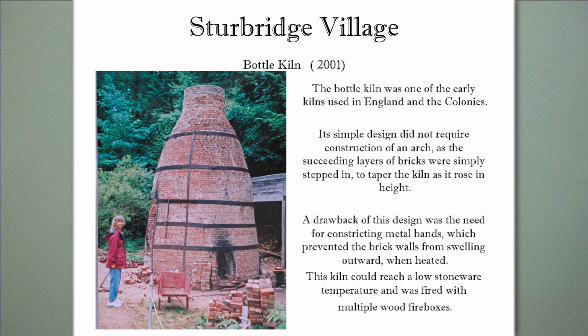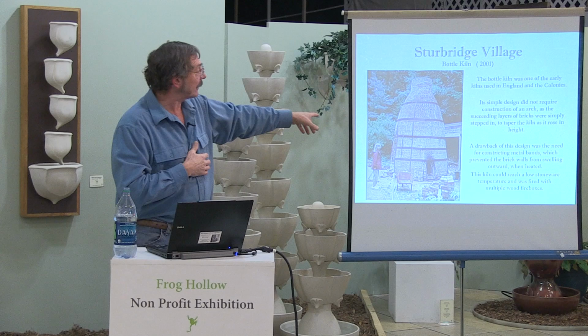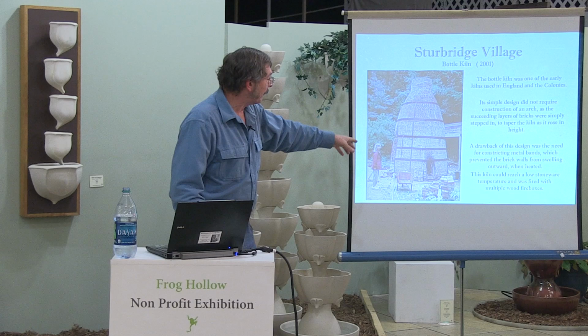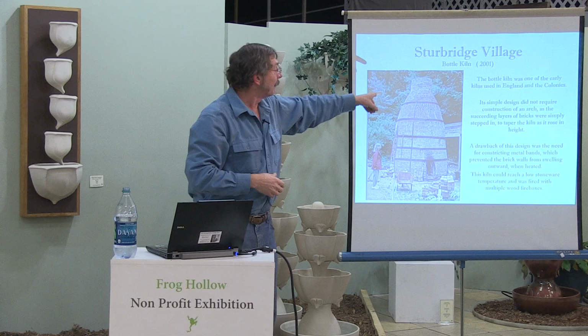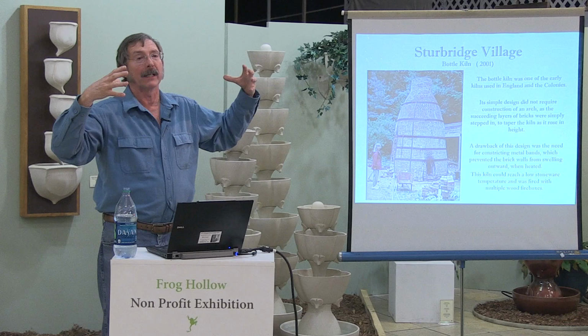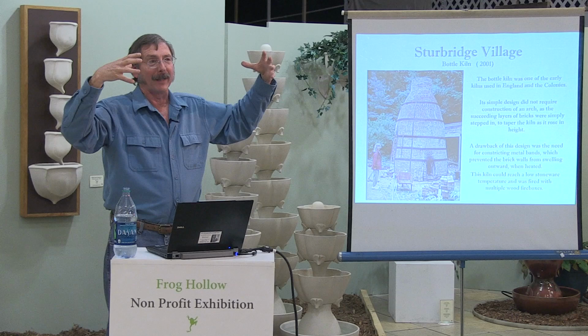But the interesting thing from a structural standpoint of being a kiln builder is you're not building any kind of an arch. You're basically just stepping in the bricks a little bit as you go up, so you don't really have to have any kind of form to structure it with, but you do need to band it, because as you heat it and the bricks expand, the whole thing is going to move out. And if you don't have something to contain it, they move out, but they don't come back in again.